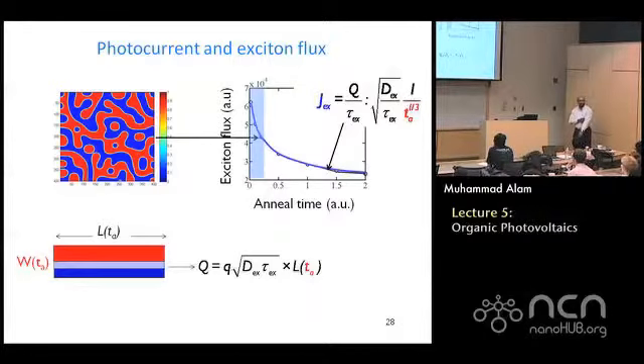Now here is a problem you can immediately see. If it is so great, if the exciton current in the beginning has a lot of area, then why should I anneal? In the beginning, I had a lot of surface area, excitons will get dissociated very nicely, I should not anneal. But it turns out that you should anneal, and otherwise the experimentalists would be wasting their time. So they have known by empirical methods that you should anneal. So what's the trick? What am I missing here?